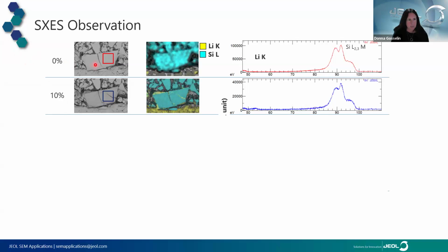What we did, this top image is at 0 charge. This is the spectrum from the soft X-ray emission. This is the X-ray intensity maps and the backscatter electron image. So at 10% charge, we're seeing a tiny little peak of the lithium there. We're analyzing in this region right here, and we're starting to see a little bit of that lithium peak and maybe some slight changes in that silicon peak shape as well.